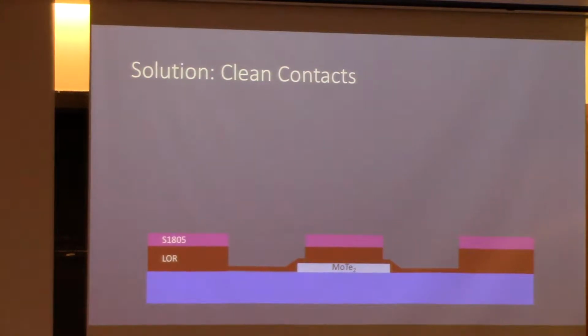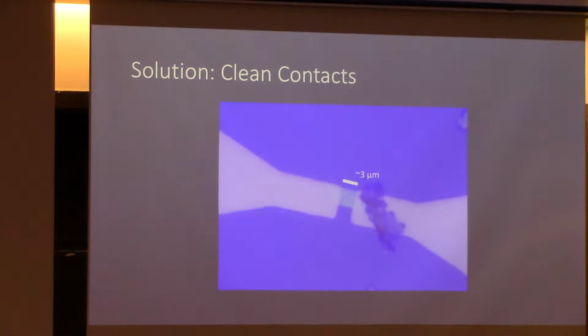And so what I decided to do is to clean the contacts with an argon plasma. Since it's hot and ionized, argon plasma is good at removing these organic molecules that the photoresist is made of. It just sort of breaks the bonds and makes them come right off the surface. So I'm actually in the process of making a device to test how well the argon plasma worked. We've already argon plasma'd it. I'm working on transferring hBN onto it now so I can take it out of the box to measure it.